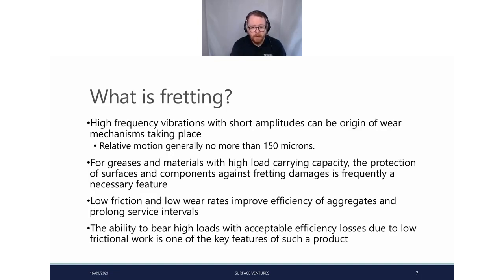For any greases and materials with load carrying capacity, we need to ensure that the surfaces are protected. If the pressure is high, if the relative movement is much higher, this creates a lot more wear particulates, wear debris, which again I'll talk about in detail a little more later. Whereas if this is smaller, we're then talking about a more fatigue-driven process. So, all important things to consider. Having low friction and low wear rates improves the service life of materials in this. It typically stops the generation of a lot of particulates, and then a higher load bearing within an acceptable efficiency range can really help in these situations.